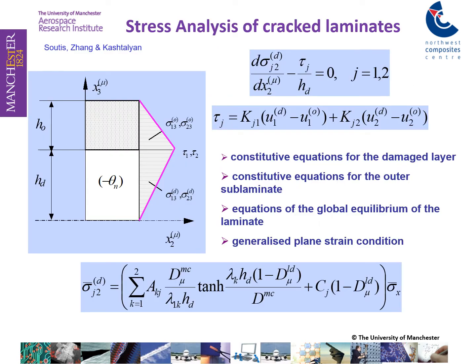The effort then is to develop mathematical models that will enable us to calculate the stresses in the cracked configuration and the damaged configuration in order to enable us to estimate what is the effect of matrix cracking on stiffness and strength, what kind of additional energy we require to develop delaminations from those matrix cracks, and ultimately perform calculations to estimate the long-term performance of the composite. And all this information will enable us to optimize the constituent properties, like the properties of the fiber, the properties of the resin, and design the interface that plays such an important role when load is transferred from the soft matrix to the hard and stiff carbon fiber.